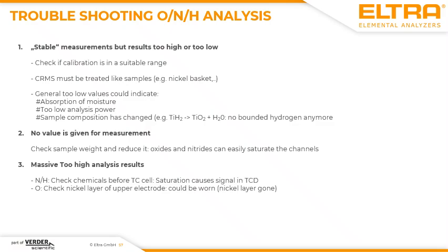if you have to. When you have too low values, then please consider that maybe you have an absorption of moisture in the powder, or that the applied power in general is too low. Or please consider that meanwhile the composition of the sample has changed, especially, for example, when you have a hydrated sample and you store it in atmosphere, make sure that the hydrogen is not lost, which happens especially with titanium hydride, for example. This titanium sample is oxidized over time and will lose hydrogen over a large period of time.